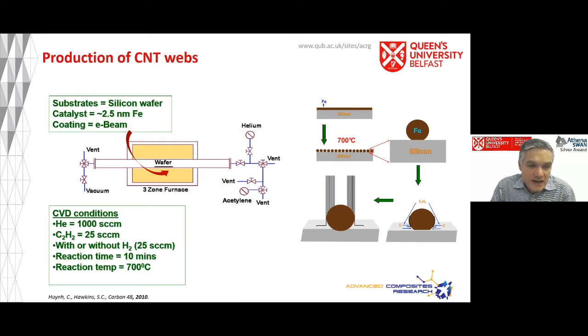And let me just bring my pointer up. As in, you grow them vertically, and we call that sort of a carbon nanotube forest. And the way we do that is that we have acetylene as the gas through which we extract the carbon, and we've got helium. There's a whole protocol on how you do this, and there has been a paper published if anyone's interested, and you can see the reference at the bottom of this slide.